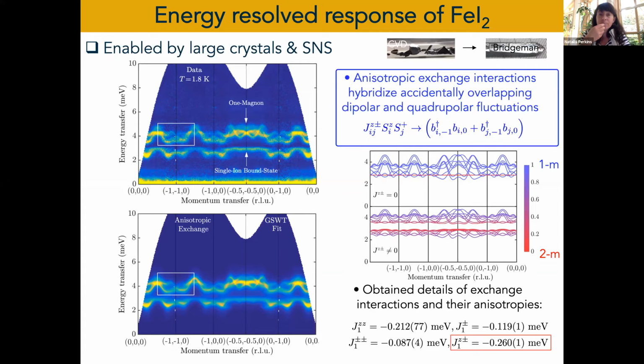And the second question is, since the Hamiltonian is so anisotropic, will you expect big anisotropy in the magnetic field response in different directions? Yeah, so it's a uniaxial magnet. We have to apply the field along the Z direction, the C axis. That's the main direction of the anisotropy. If you magnetize in the other direction, the response is quite different.